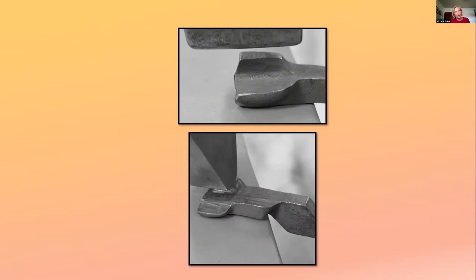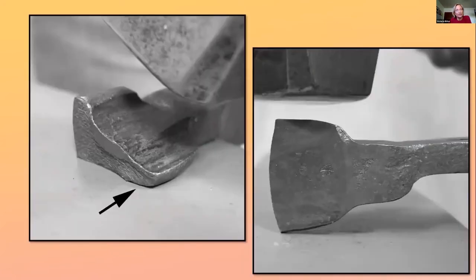If you'll notice, you end up with kind of a ridge here as you fuller that out or as you cross peen that out. This can create a cold shut if you don't use the flat side of your hammer to make sure this is all flat as you go along. You should end up with this hammerhead shark kind of look as you go forward.